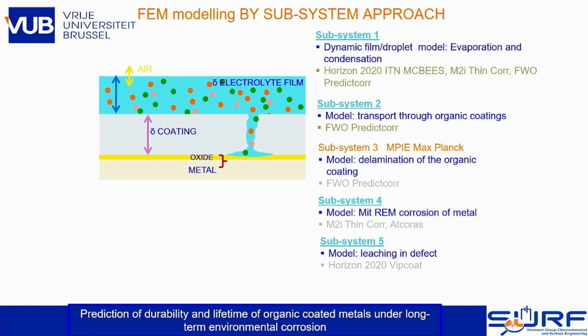So one is a model in which we look at what we call the dynamic film droplet model. This is still on the bare substrates, which we are trying to bring into the leaching model in the future. This is actually a prediction of the corrosion under a thin film or under droplets. Subsystem 2, which I will show you in a minute, is the transport through the organic coatings.